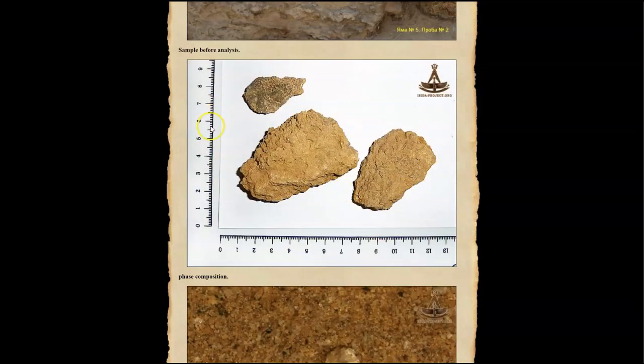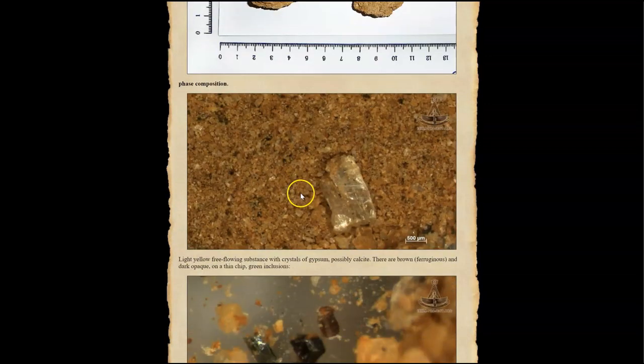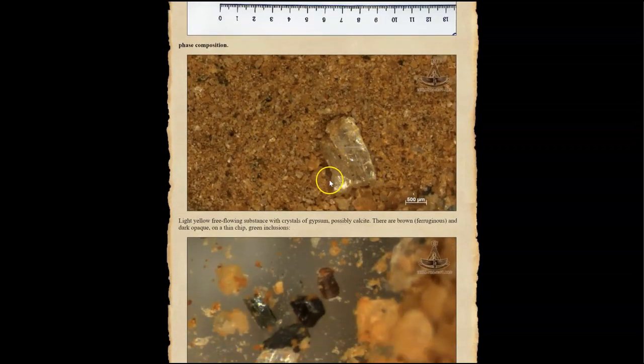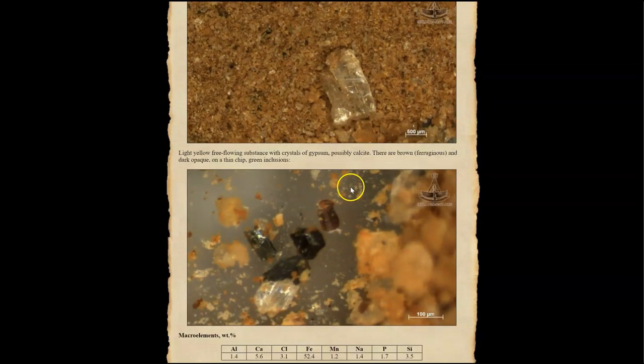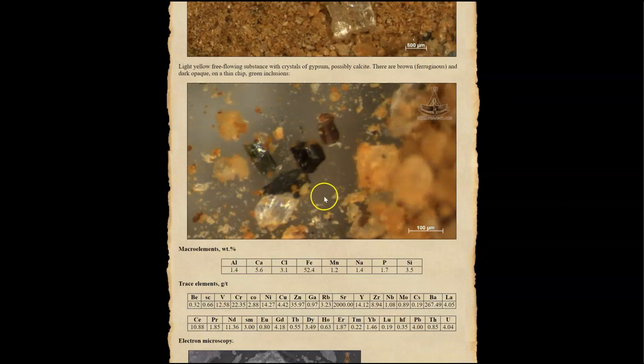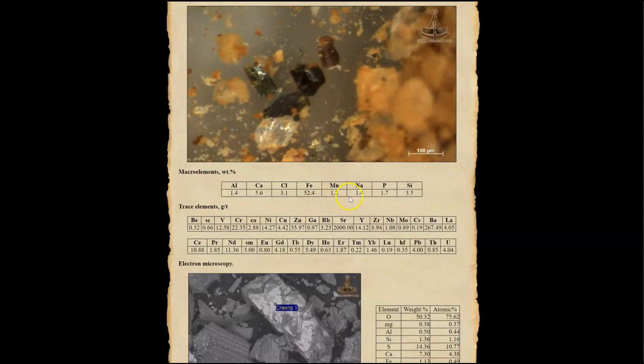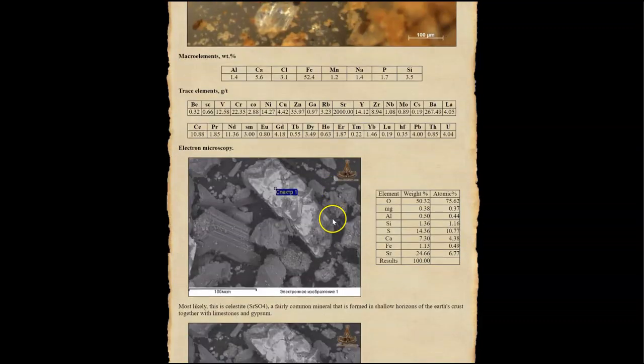an image of the material, which looks quite different than the previous ones, as you will see reflected in the chemical analysis. A close-up here showing a little gypsum crystal, more crystalline material within the microscopic fragments here. And we have the sample coming in with a macro analysis at 52.4% iron. On the scanning electron microscope, we see more celestine, the strontium sulfate.